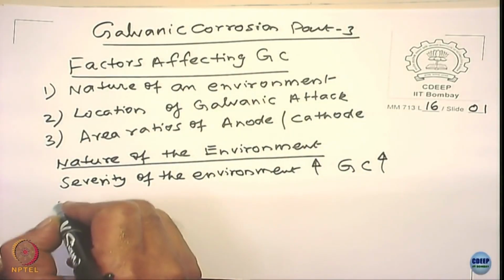One is the corrosion in magnesium sulfate, which is a relatively mild environment, and the other is corrosion in sodium chloride solution, which is a relatively severe environment. Take the two metals, steel and zinc. If you look at the corrosion rate of these two metals in uncoupled and galvanically coupled conditions, you will see how the corrosion of the zinc, which is more active, changes significantly if the environment becomes very severe. This is data taken from the Fontana book. You can just have a feel for it.